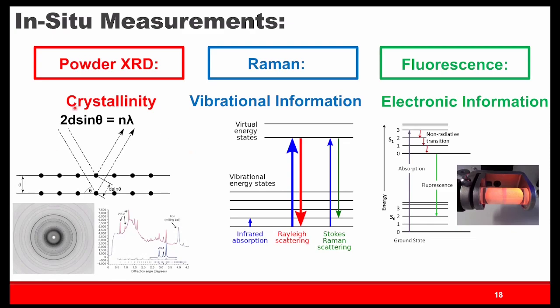The main one is powder X-ray diffraction, where we're looking at the crystallinity. Remember, we're doing our reactions in the solid state, and they're largely of crystalline materials. So we can actually use powder diffraction to monitor the reaction, which is something you can't do for solutions because it's dissolved, and so your material is not going to be crystalline. We can also use Raman spectroscopy to look at the vibrational information. This vibrational information can be really useful for looking at the different species and different compositions, even if you have a reaction mixture that's not very crystalline. And finally, one of the things that I've spent a lot of time working with is fluorescence spectroscopy as another means of getting some electronic information and trying to understand what's happening in these reactions.